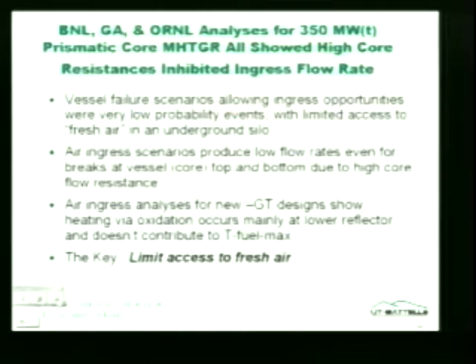This is an example of an experiment the Germans did where they did that kind of thing. This shows how much oxidation took place in various parts of the core. This is the lower reflector. This is the core area. You see it's predominantly in the bottom. If you have a double break such that you have access to the bottom and the top with unlimited supply of air, you get a lot more oxidation. Sometimes that oxidation can creep up into the fuel area.